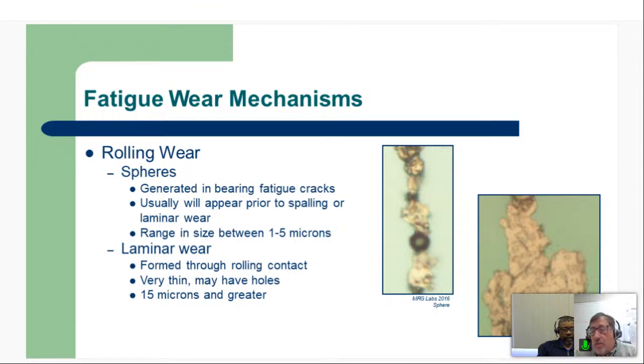And I should say that most of the pictures we're showing here, and maybe we'll start on the microscope, are with the green transmitted filter in place. And then you see that green light coming up, and it helps you pick out the edges of the particle. But when you see the green in the middle somewhere, then it's like, well, yeah, I'm seeing right through it, right? So I've got a hole in there. It's so thin, a micron or less, that you actually get holes in those particles as they form up.